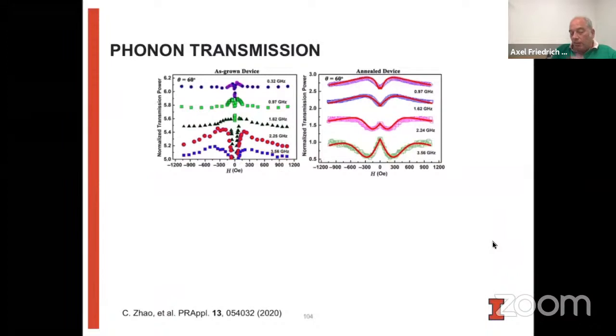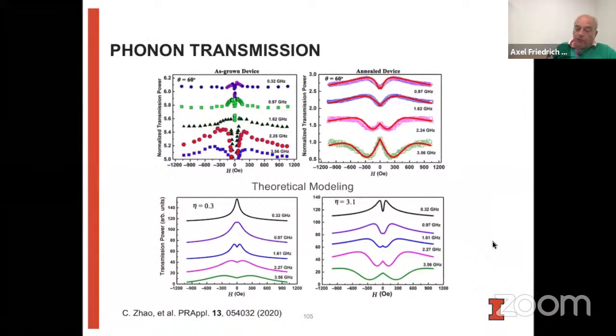So this is just another way of plotting this. In the annealed device, we have these well-defined minima, while here, if anything, we have even slight maxima at around similar fields. It turns out you can model the behavior of these two samples very well by having everything the same. The only thing that you change is the strength of the interfacial coupling, which in the annealed device is about 10 times larger than in the as-grown device.